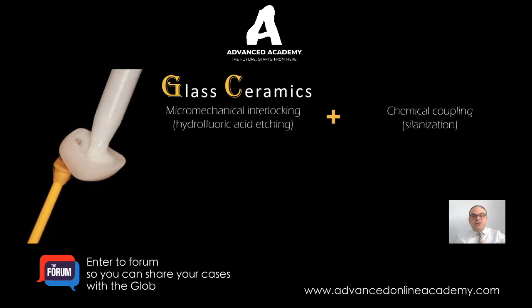Now, glass phase ceramics. It's a combination of micromechanical interlocking using hydrofluoric acid etching with chemical coupling. For feldspathic porcelain, you apply hydrofluoric acid 10% for 60 seconds. Please pay very close attention to the concentration of the acid and also the time that you're applying it. These can be detrimental to the outcome of your restoration. If you etch with a higher concentration of acid, or for a longer or a shorter period of time, it will affect the bond strength to the tooth structure. So for feldspathic porcelain, you use 10% hydrofluoric acid for 60 seconds.